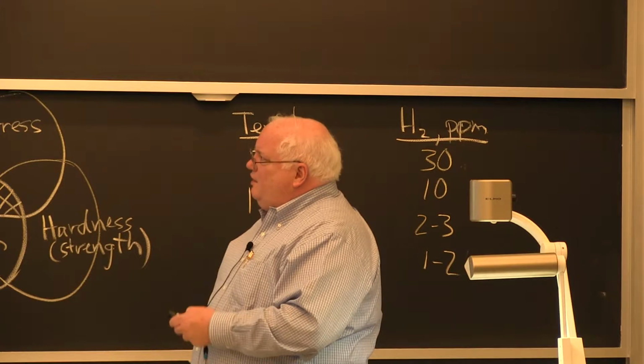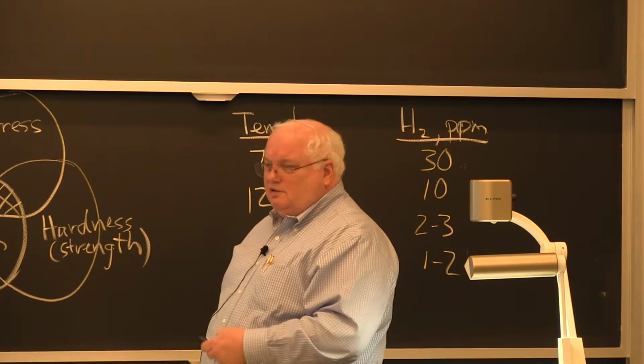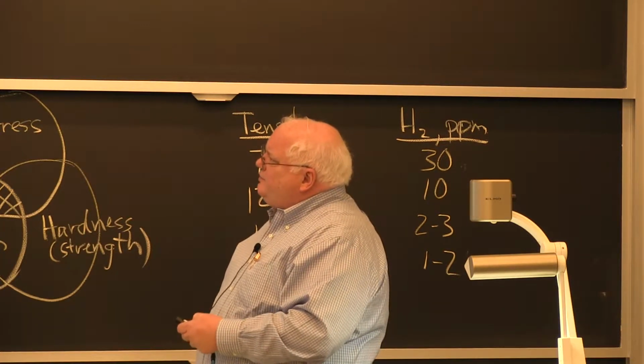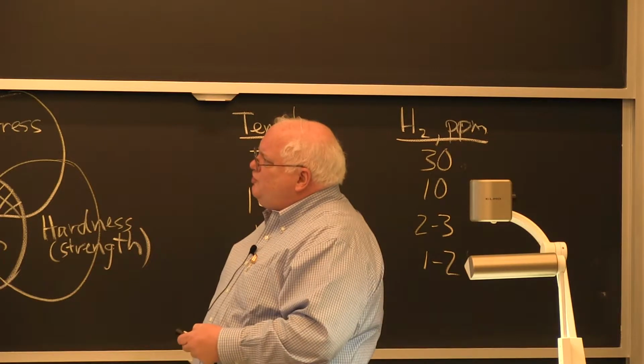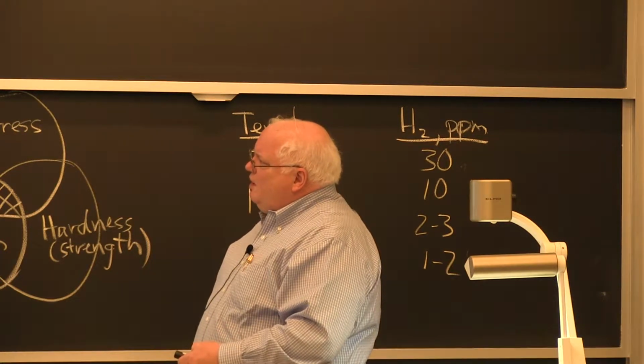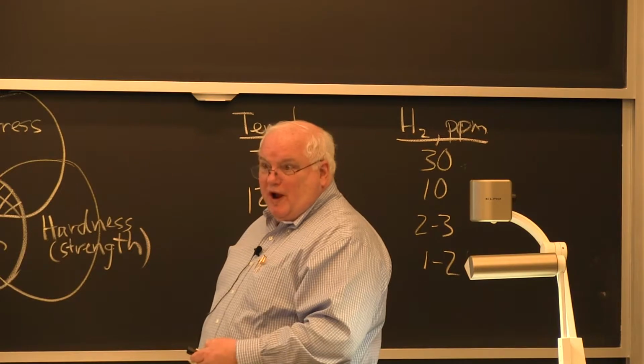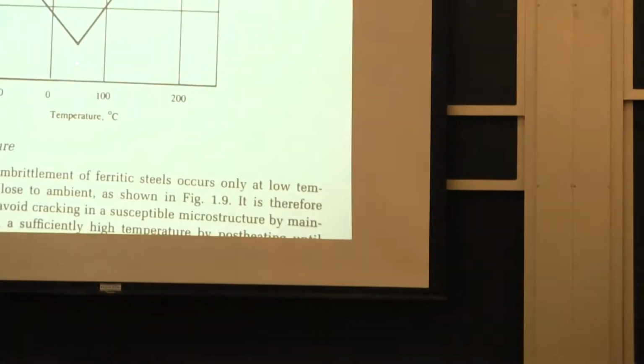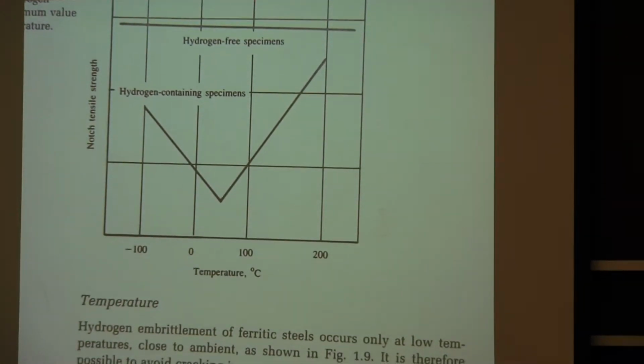So the point here, getting back to welding, unless there's other questions, is you can get rid of the hydrogen at higher temperatures than room temperature. You can lock it so it doesn't diffuse around to do its damage at lower temperatures. The absolutely worst temperature is right around room temperature. Lucky us. That's where we live, and that's where hydrogen is the worst.